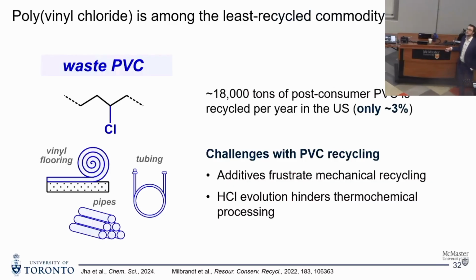PVC is one of the third or fourth highest volume plastics in the world, but it's one of the least recycled, and that's because there are a lot of chemical and mechanical challenges associated with the wide variety of vinyl materials we use. It's in flooring here, it's in soft materials, it's in rigid pipes. So it has a lot of different additives that make it hard to separate and distinguish. And because it has this chlorine, if we try to do anything thermochemical, if we burn it, if we pyrolyze it, we release a lot of gaseous HCl, which is really problematic for reactor equipment. Not to say it can't be done, but it has its challenges and adds a lot of cost.